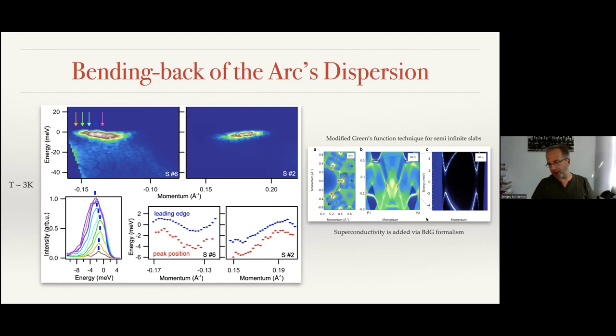Again, our colleagues simulated the superconductivity on the arcs, using the Bogoliubov-de Gennes formalism, and they added superconductivity in this case to the arcs. And indeed, this was a very good qualitative agreement with the experiment. Even quantitatively, one could see that the bulk remains non-superconducting and the surface is superconducting.